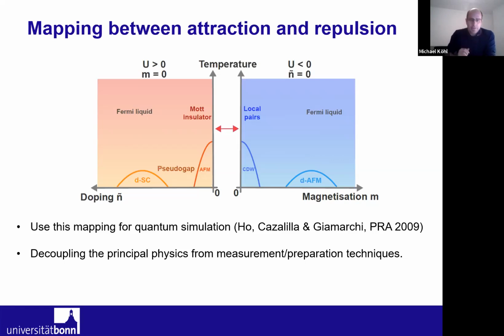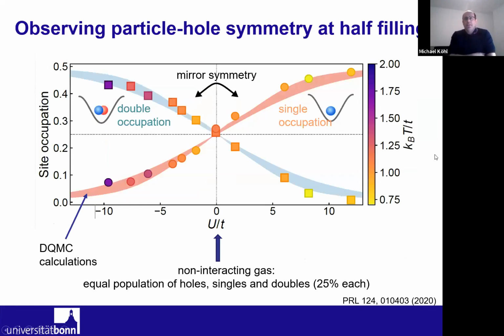And so far this was only a theoretical concept, and we would like to see how well this is actually realized in the experiments. Okay, so the first thing that we did is we went to half filling. So the situation that I described initially, we have equal number of particles in spin up and spin down, and total number of particles is equal to the total number of lattice sites. On average, 1 particle per site. And now we change the interaction and look at the single occupation and the double occupation.